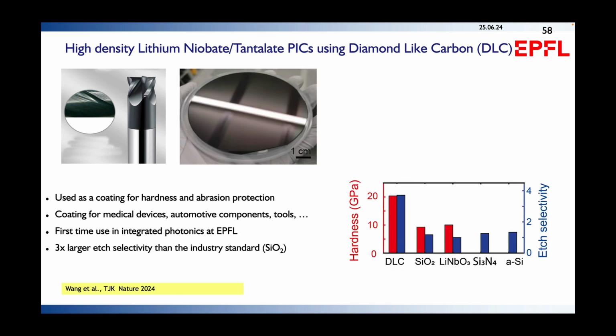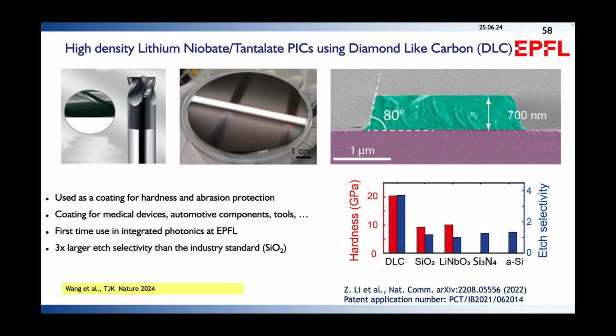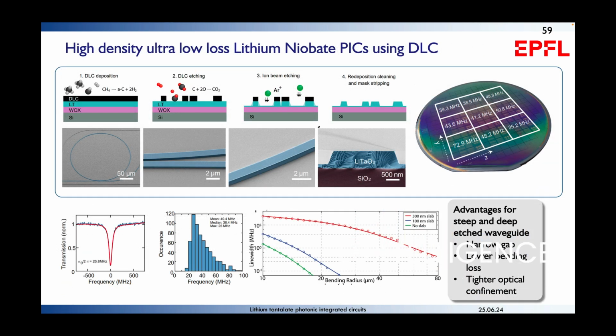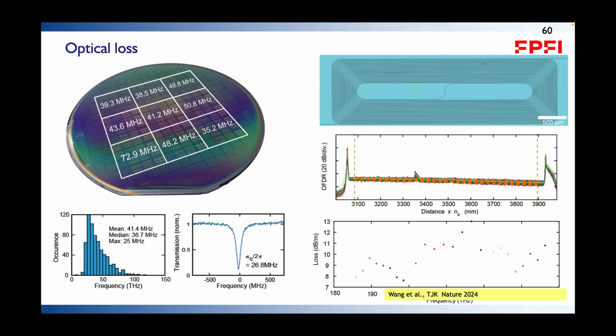But it has one very beneficial property when it comes to integrated photonics. It has an extremely good hardness. If you compare the hardness of DLC to lithium niobate, it's substantially harder. And so this means it's a very good hard mask to etch this material. What we've shown is that with this material we can etch deeply, confining waveguides with almost vertical sidewalls. And what's even more interesting, we can get very low optical losses, less than 10 dB per meter. The best losses we see are 3 dB per meter, which is almost on par with what we can do with lithium niobate. And this we also commercialized, as said, with a pure-play foundry, Luxtelligence. This is an example of one of these devices.